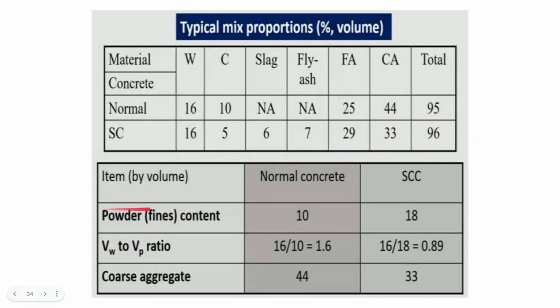So if you compare the powder fine content, one is having 10 and one is 18, 5 plus 6 plus 7. So volume of water to volume of powder ratio, both are having 16% of water by volume. So 16 by 10 is 1.6 and 16 by 18 is 0.89. So the water to powder ratio in self compacting concrete is lesser than 1, and in case of normal concrete it is greater than 1. It is 1.6. So that is the general parameters, general values.